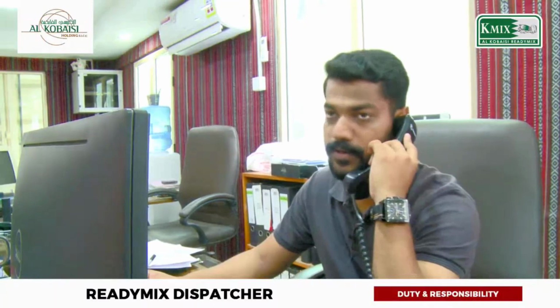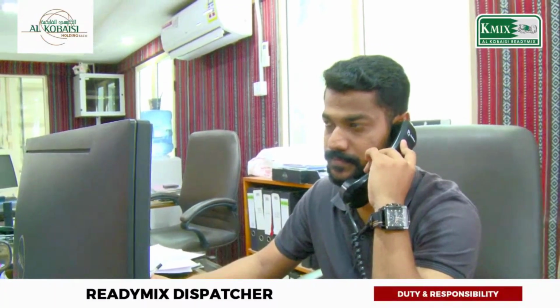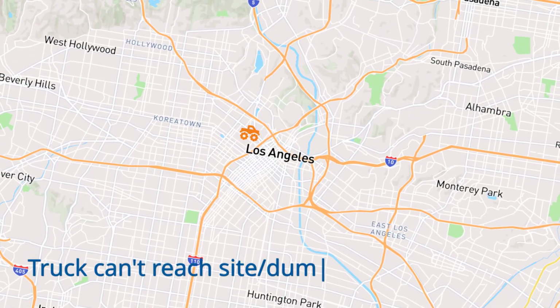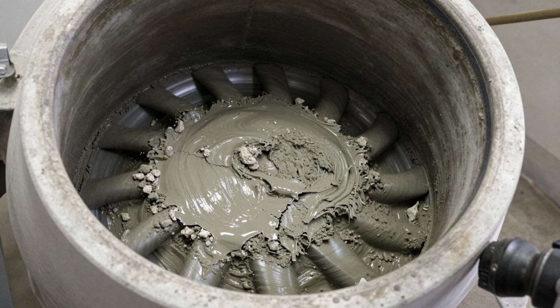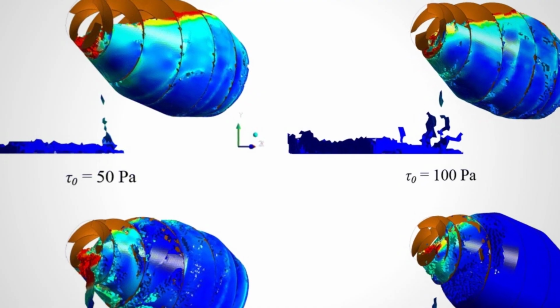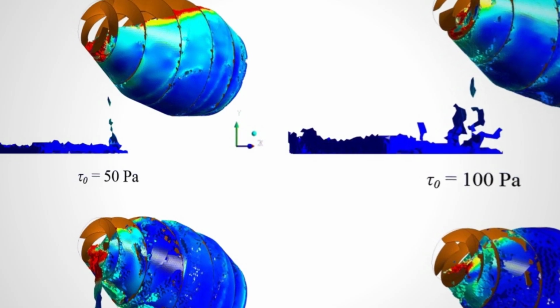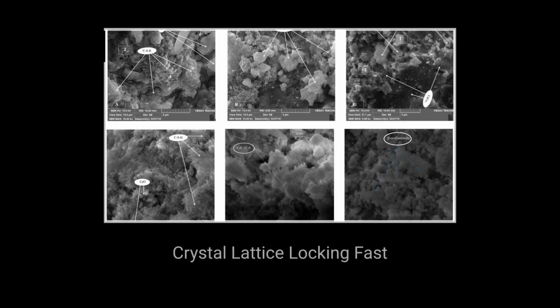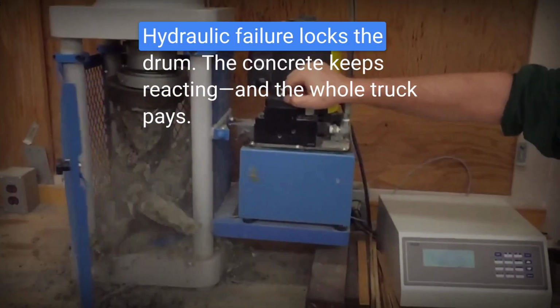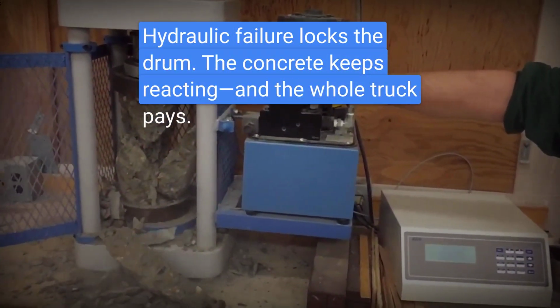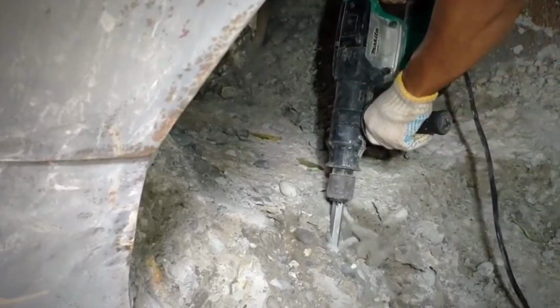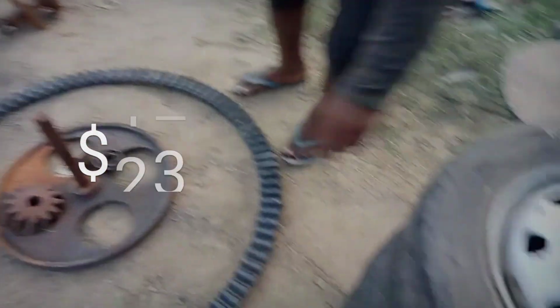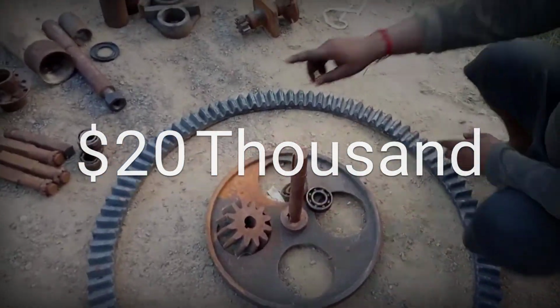And here is where drum failure becomes an emergency. When a hydraulic pump fails in transit, which does happen, dispatchers do not treat it as a breakdown to be scheduled. They treat it as a race. If the truck cannot reach the job site or an approved dump site before the hydration clock runs out, the load will set inside the drum. Partially set concrete, subjected to forced rotation, tears apart the interlocking crystal structure rather than breaking up cleanly. The result is concrete with compromised strength that looks fine but is not, and a drum that may require hours of jackhammering or even full replacement. Drums cost between $10,000 and $20,000.